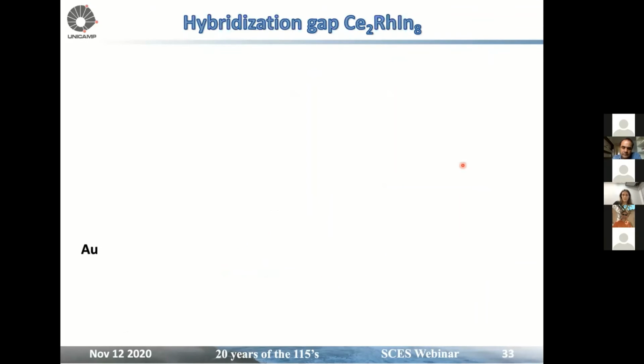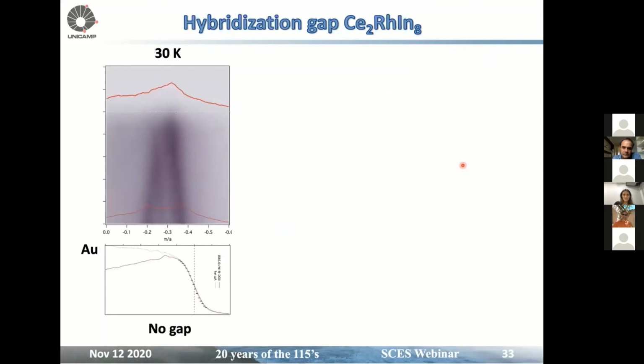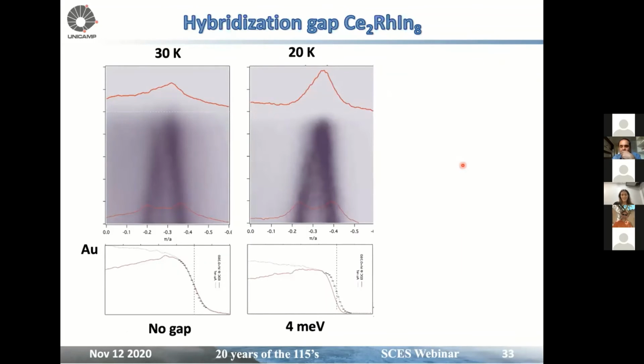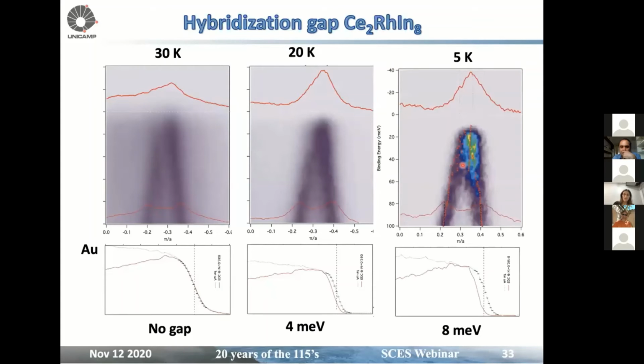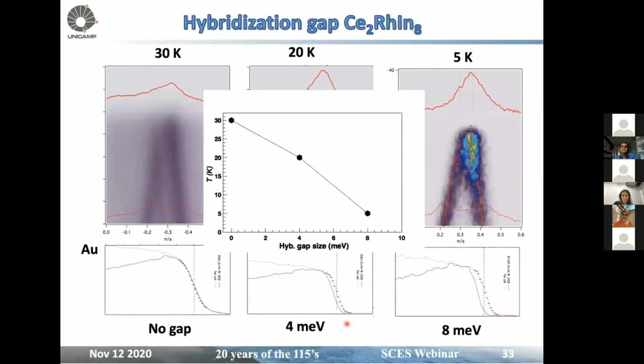So we can then do that as a function of temperature. So that's 30K, no gap; 20K, we see about 4 meV. And if we go to the lowest we could go, at 5K, we see 8. So you're going to remember I told you my resolution was about 15. So yes, we are inside our resolution, but even so it's a behavior that we could follow as a function of temperature. So it's hard to quantify the size of the gap, but I tried to show you here the gap as a function of temperature for those points I have.